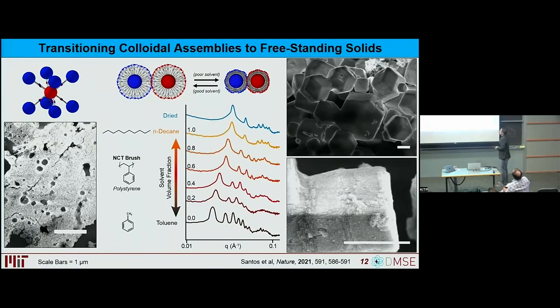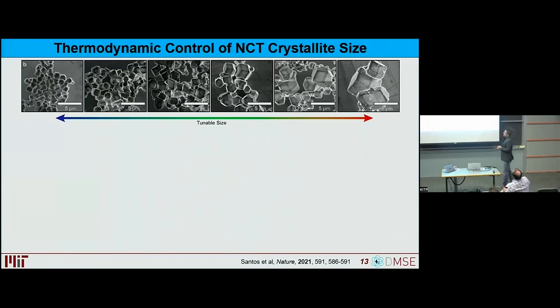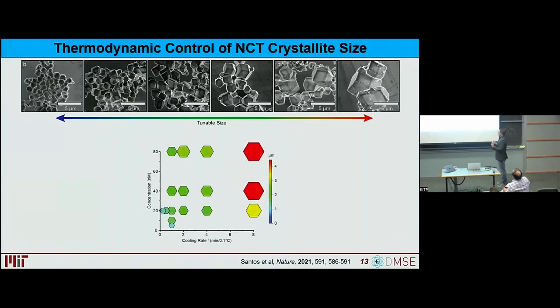And what we find is they form not just ordered structures, but they actually form these well-defined Wulff polyhedra, these things that have facets on them. So these are very nice, very interesting structures for being able to understand different types of assembly methods. What's nice about this is we can tailor the size of these as a function of a couple of different variables. For example, the cooling rate. The slower we cool the material, the larger the crystal gets. And the larger the concentration of the sample is, the larger the crystallite we see actually is.